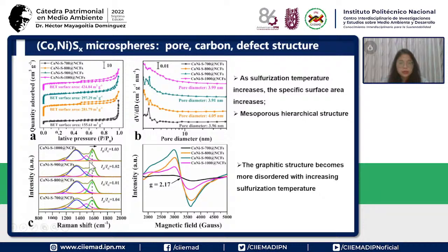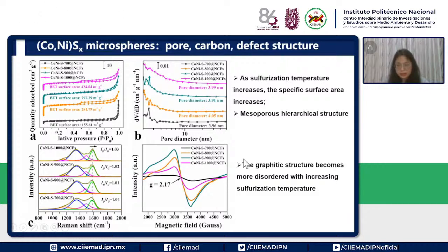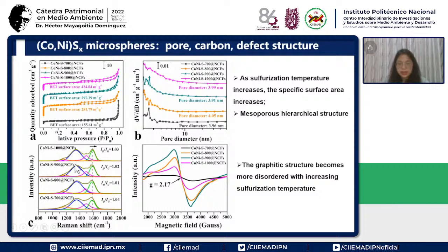But for the carbon structure, there is not much change. Only the G band is shifted to the higher region, maybe because it comes from more carbon defects. And then we test the vacancy here. This value is also related to the metal vacancies, as indicated by the EPR analysis.